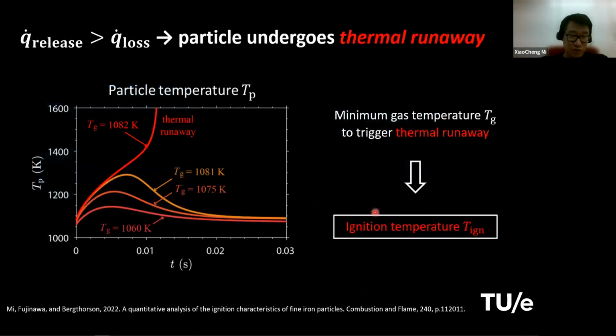And we use just simple heat and mass balance equations. We solve that, and we can get the result of particle temperature as a function of time, but for different gas temperatures. So you can see for some relatively low gas temperature, below a certain value, the particle is being heated up a little bit, and then cools down, and then eventually becomes the same temperature as the